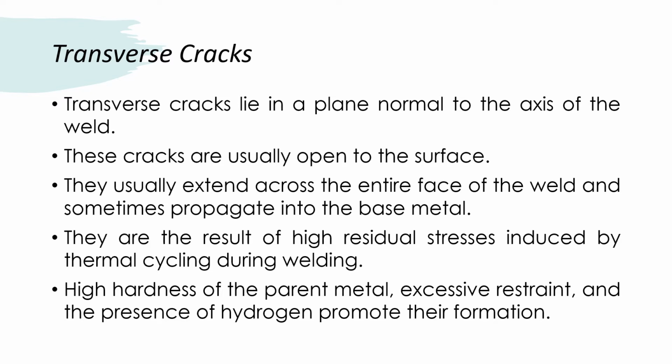Now we discuss transverse cracks. The transverse cracks lie in a plane normal to the axis of the weld. These cracks are usually open to the surface. They usually extend across the entire face of the weld and sometimes propagate into the base metal. They are a result of high residual stresses induced by the thermal cycling during welding.